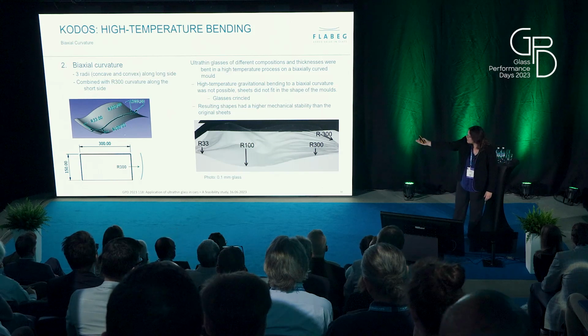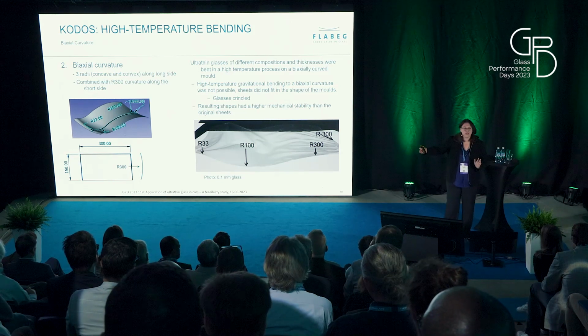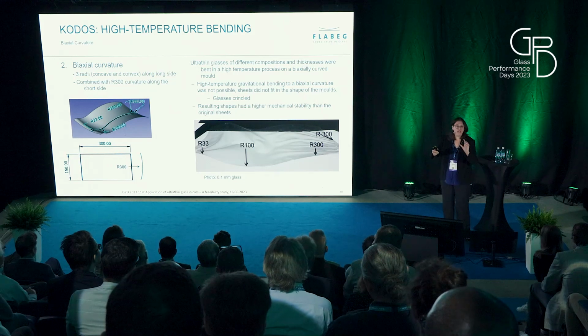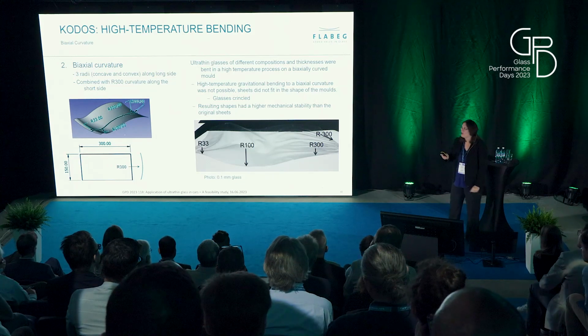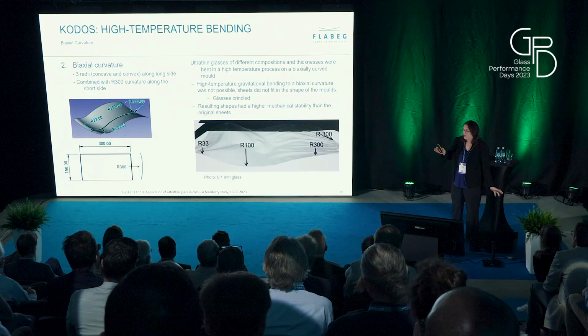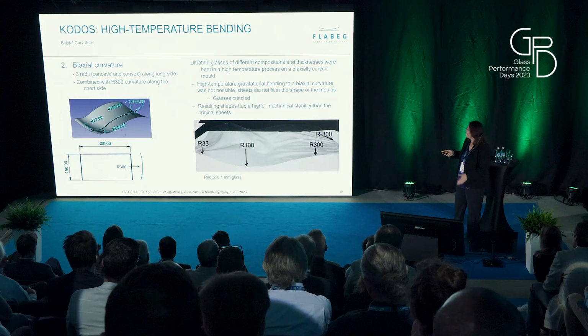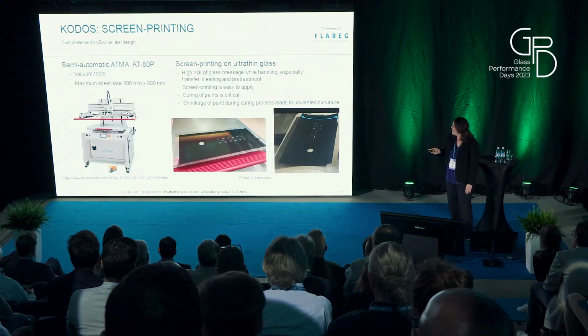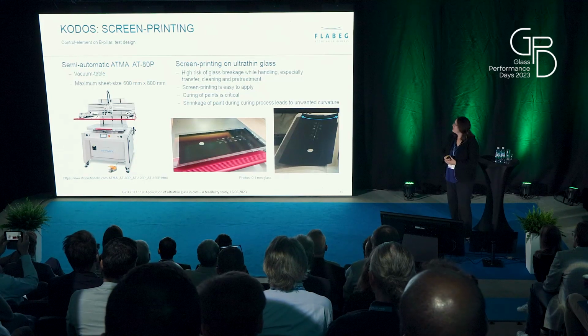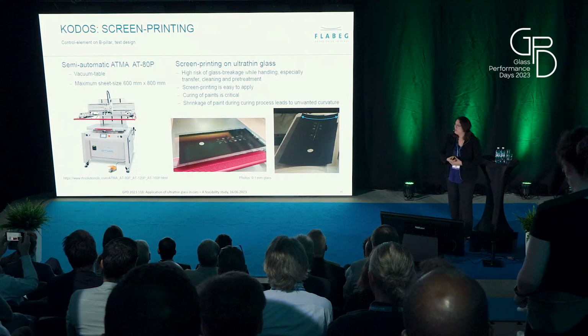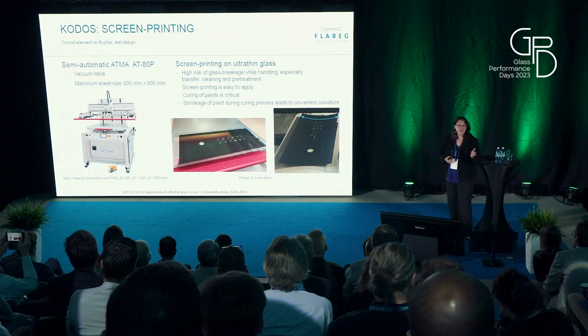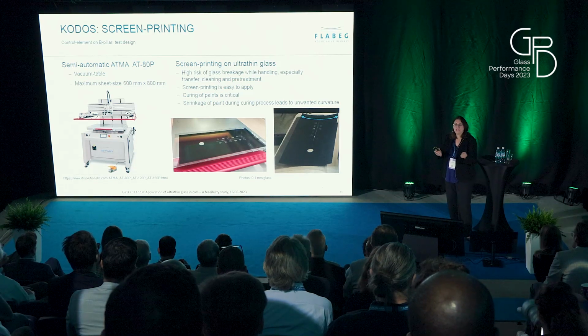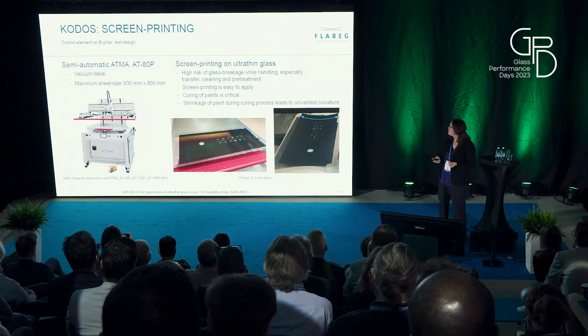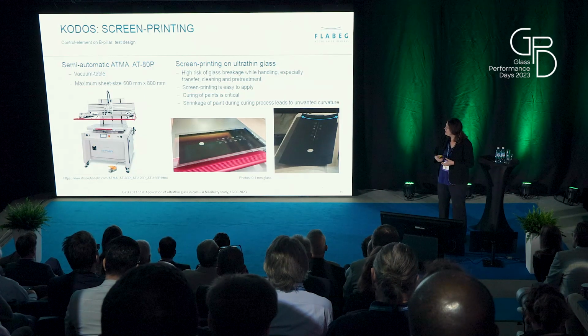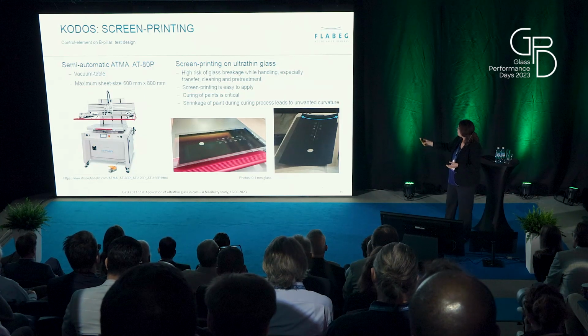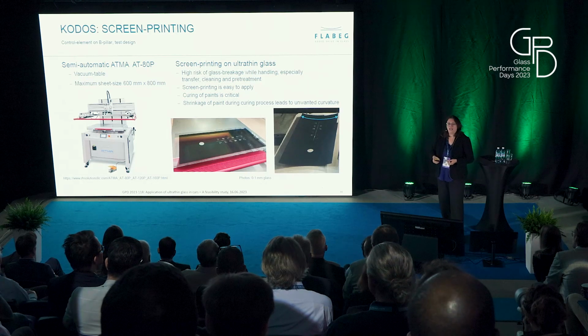Let's say I think it's 300 millimeter in size and 150 millimeter. So maybe if you have smaller samples, it might work more easily, but here, at least with gravity bending, there's a stop. Yeah, but functional coatings like screen printing here work quite well as long as you choose an ink which is not shrinking too much. So if you cure the sheet, the layer, then you might have the problem of curvature again.